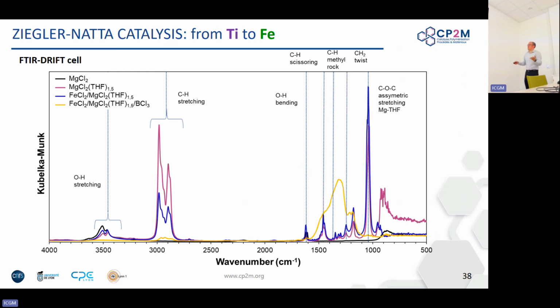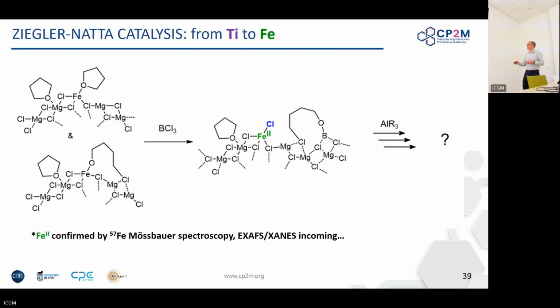A little bit of spectroscopy, as I said, the role of the Lewis acid treatment is once again to remove the alkoxides. So these are these bands. They correspond to the bonds that you would form upon removing all the iron oxygen bonds that you would have formed on precatalyst synthesis. This is to give you a rough picture. We do believe that we start with an iron 2 chloride center, and something happens to this iron 2 chloride center when we do the alkylation reduction.